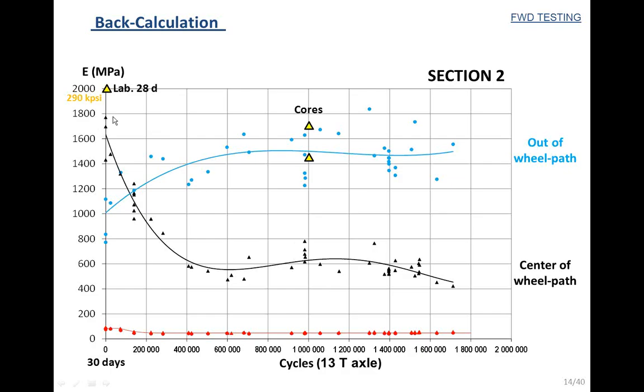So you can see that at the beginning of the test the modulus was around 1500 megapascal, and remember that we were expecting 2000 megapascal from the laboratory. I should say that when these 3 points were obtained, the age of the material was around 30 days. So this modulus should be very close to this modulus. And in fact, we believe it's very close, but we had the feeling that we were underestimating the modulus of this material at the beginning of the test.